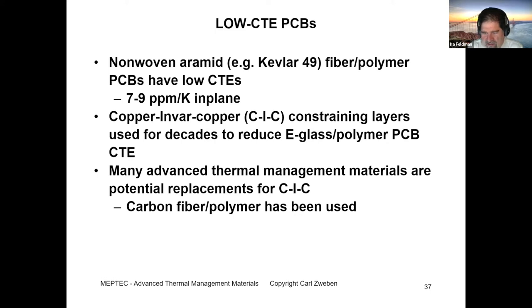Talking more about anisotropic, there's a question here: does the fact that some MMCs are anisotropic cause stress in other directions, especially if you have a wide area that you're interfacing to? Not necessarily. It's going to depend on the geometry of the component. For example, if I apply an anisotropic layer to a printed circuit board, if I match the coefficient of expansion of the printed circuit board with the composite layer in the in-plane direction, there will be no thermal stresses. So it's going to depend on the geometry. Okay, got it.